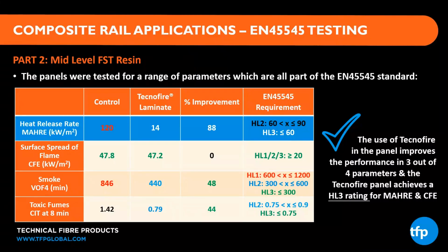And the toxic fumes, you can see, is very, very poor. We've got a conventional index of toxicity of 1.42. This is a halogenated resin. So as we mentioned at the beginning of the presentation, these systems work by liberating toxic gases that are very effective free radical traps, but are going to fail a toxic fume standard like 45545. And if you look at the parameters, that's outside of the parameters of this standard.